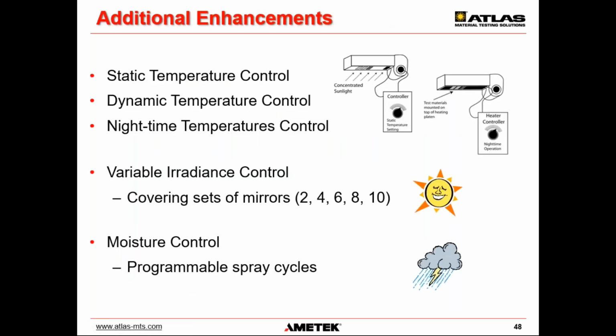Now there are additional enhancements that we can do. We can control temperature with a variable speed fan. We can actually control the temperature to a replicate sample, take temperature measurements of a sample on exposure, let's say in Arizona, and then basically match that on this type of a device. We can also put the samples on top of mat heaters to control nighttime temperature as well. If the intensification is too high, we can cover sets of mirrors and also have programmable spray cycles beyond those 3 that I referenced earlier.